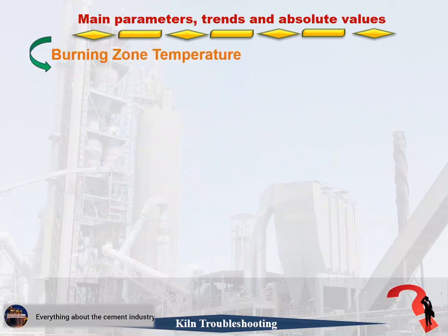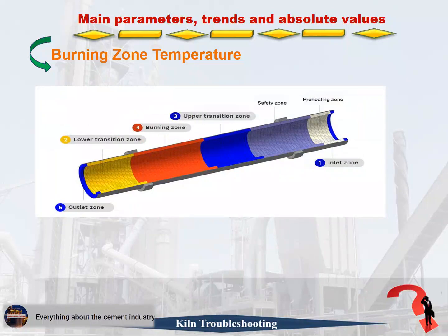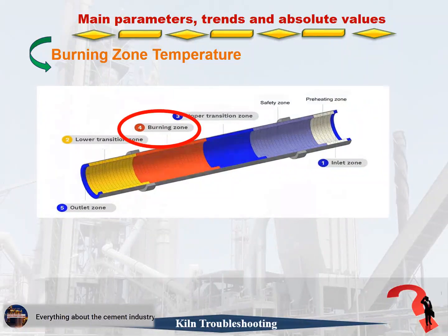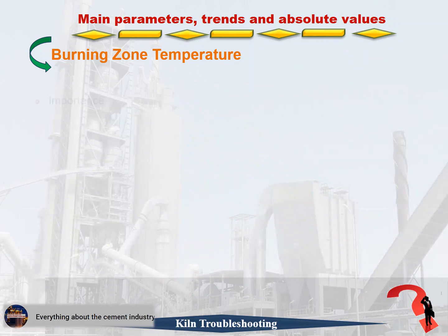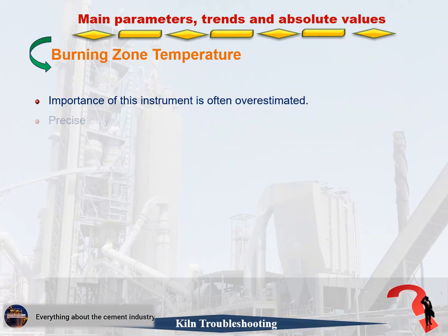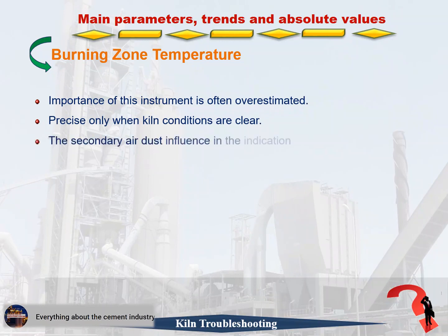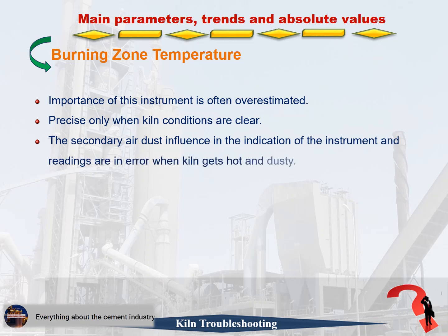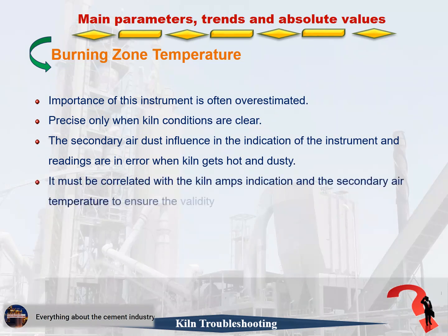Burning zone temperature. This picture shows an area burning zone at kiln. 1. Importance of this instrument is often overestimated. 2. Precise only when kiln conditions are clear. 3. The secondary air dust influence in the indication of the instrument and readings are in error when kiln gets hot and dusty. 4. It must be correlated with the kiln amps indication and the secondary air temperature to ensure the validity of the reading.